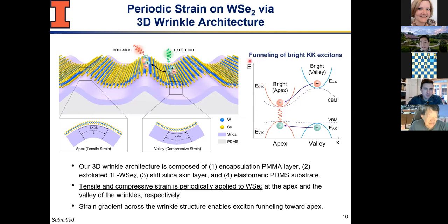And if you show that in band gap or energy of your electron hole, at the apex and the valley, here the dotted line shows how conduction band and valence band changes. But at the end of the day, what we wanted to see is at the apex, what is this energy. This is, when light shines, the energy of the photon that will come out. So this is your band gap energy. And as you can see, as a function of valley versus apex, you're seeing different levels of band gap, particularly the conduction band changes a lot. And that gives you strain control, band gap energy control in real space.